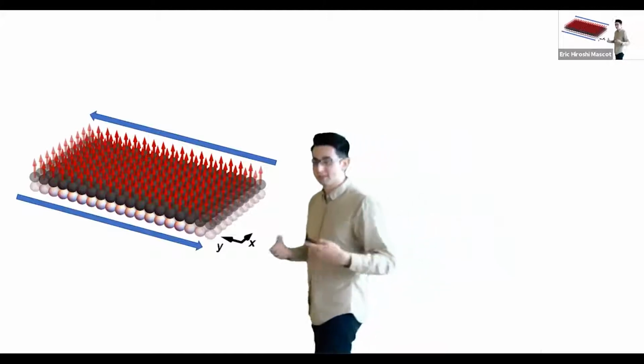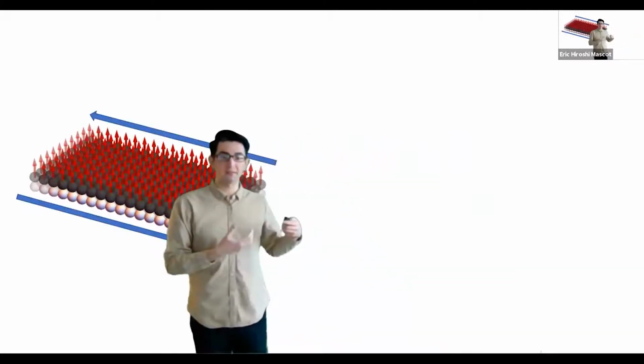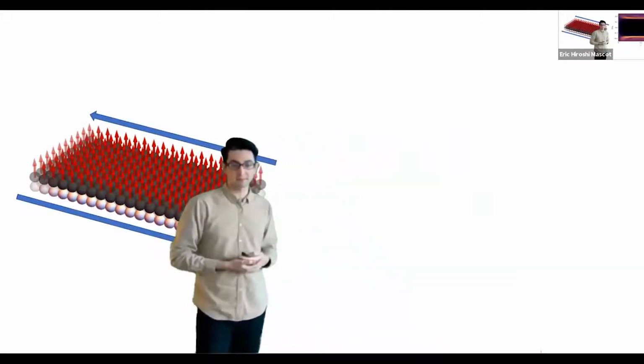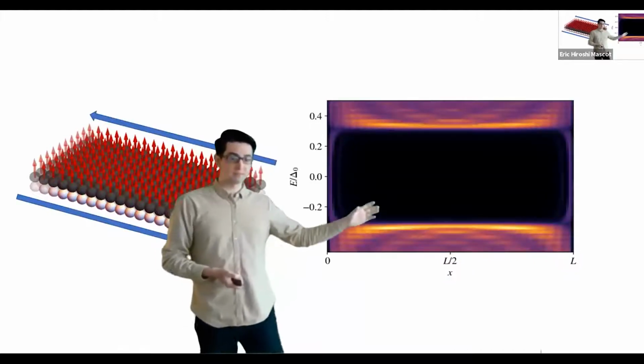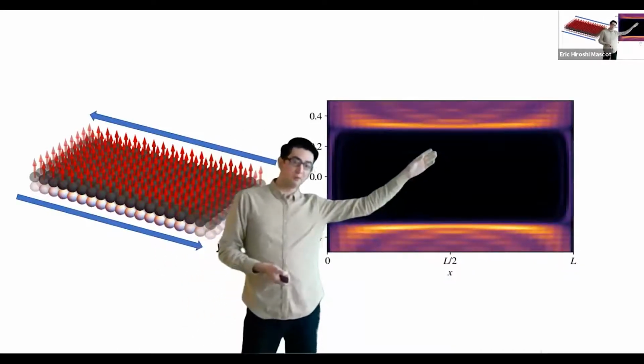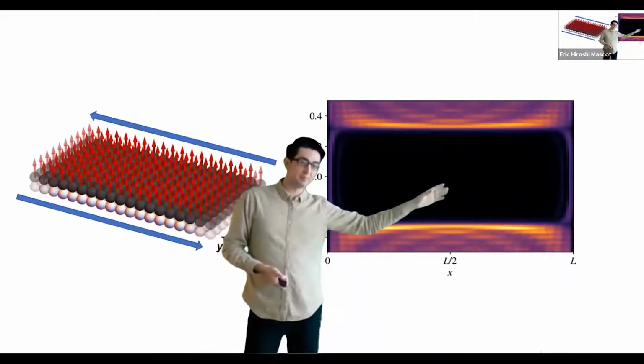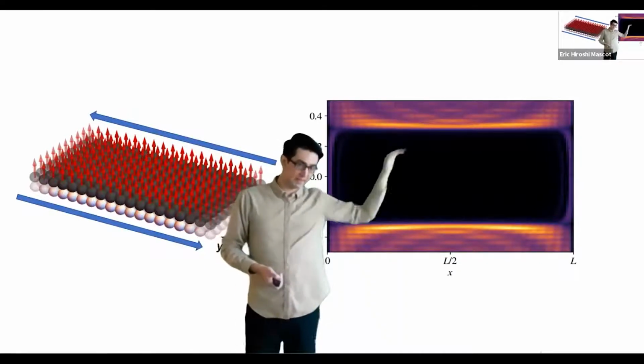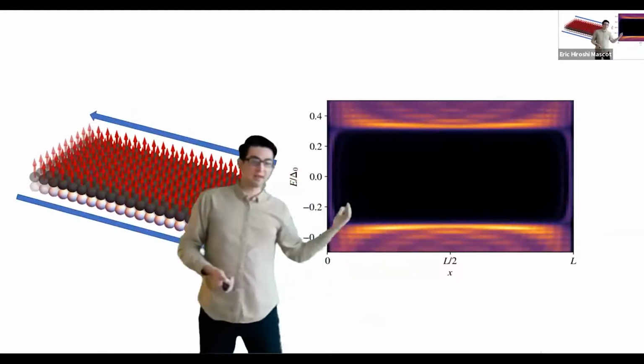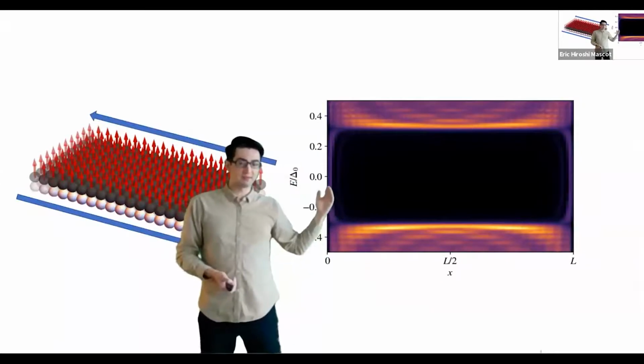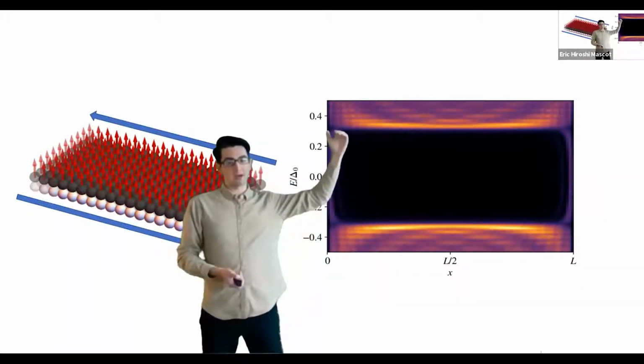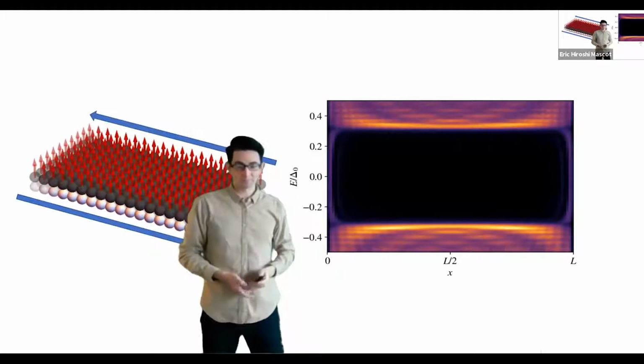And so to see if we have a state at zero energy, we look at the local density of states. And so in the bulk of the system, in the middle of this ribbon, we don't see states inside of the gap. And then we see the superconducting gap up here. And then at the edges of the ribbon, we see a state at zero energy, and it also goes all the way up to the superconducting gap.